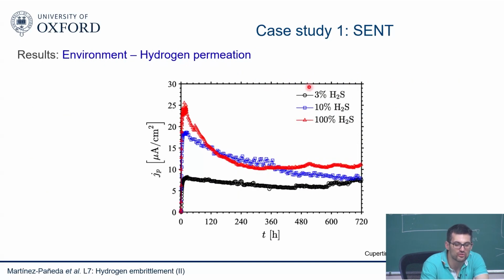Some hydrogen comes in. H2S is a poison in that it slows down the process in which hydrogen recombines and goes away, and therefore more hydrogen comes in. So that's why traditionally hydrogen embrittlement was a big problem for H2S environments. It still is, but the first times we started to be worried from an industrial perspective about hydrogen, even though we were working with materials that were not very susceptible, was the fact that we had this big amount of hydrogen coming in. So there's a lot of hydrogen coming in, but then something happens.